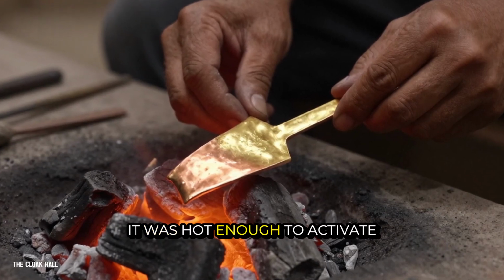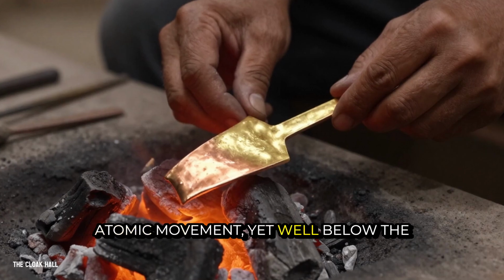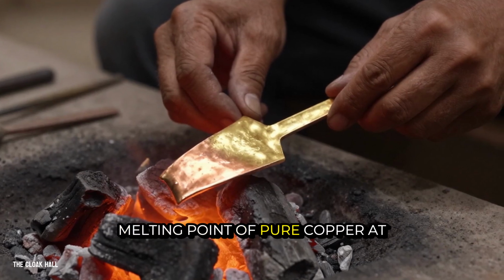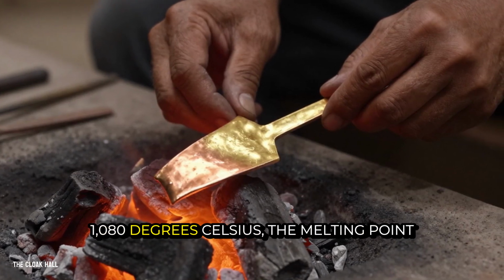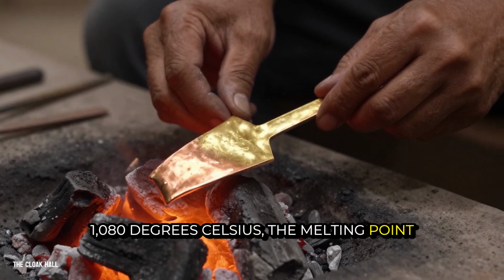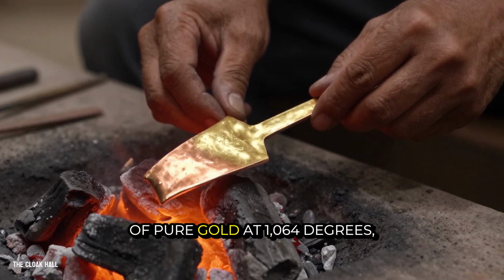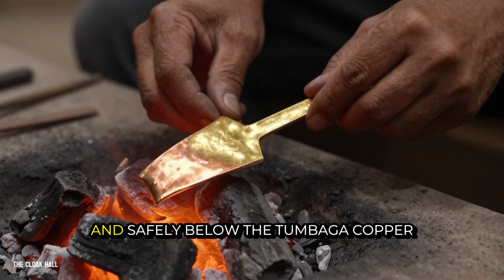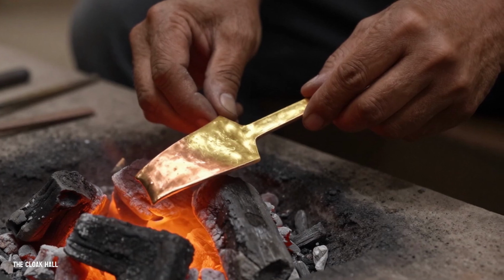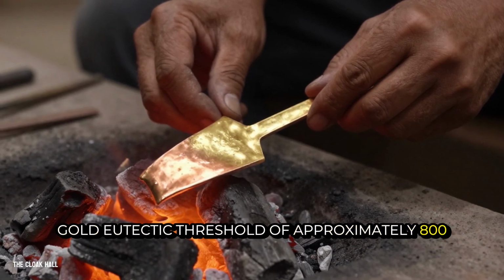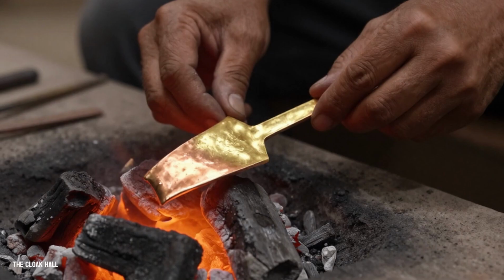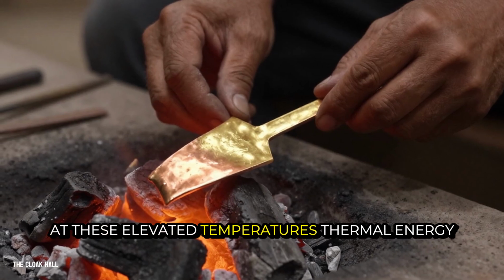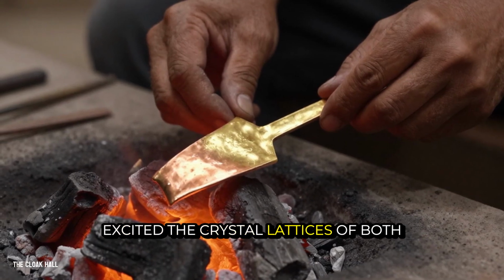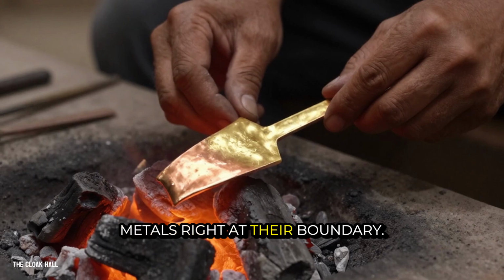It was hot enough to activate atomic movement, yet well below the melting point of pure copper at 1084 degrees Celsius, the melting point of pure gold at 1064 degrees, and safely below the tumbaga copper-gold eutectic threshold of approximately 800 degrees. At these elevated temperatures, thermal energy excited the crystal lattices of both metals right at their boundary.